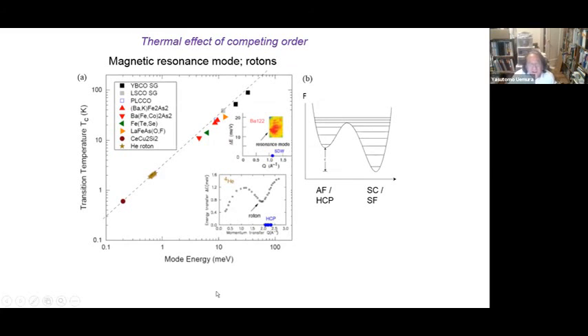So that is not only for the case of cuprates. This is a logarithmic plot of Tc versus mode energy, and these are the spin gap energies of the cuprates. But we also plot the various resonance mode energies for iron-based and iron selenide superconductors, the heavy fermion CeCu2Si2, and helium roton with various pressures is shown here. So they have almost exactly the same ratio.